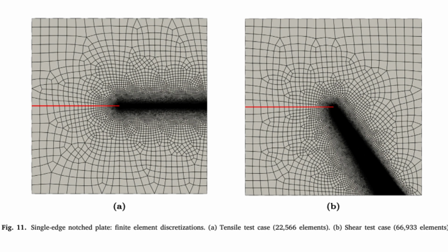If you absolutely needed your simulation to run without crashing, especially during those unstable moments, you traditionally relied on something called the alternating minimization algorithm, or AM, sometimes called a staggered algorithm. Okay, AM. Why was that the go-to? Well, it's robust because it cleverly sidesteps the trickiest part. It decouples that complex non-convex problem into two simpler sequential steps. It solves for one variable, then the other, back and forth. It basically guarantees convergence. It just works.